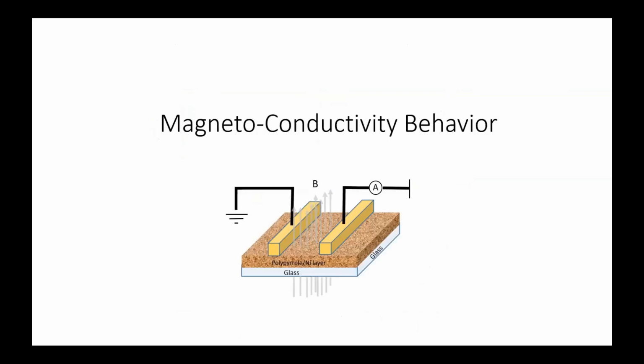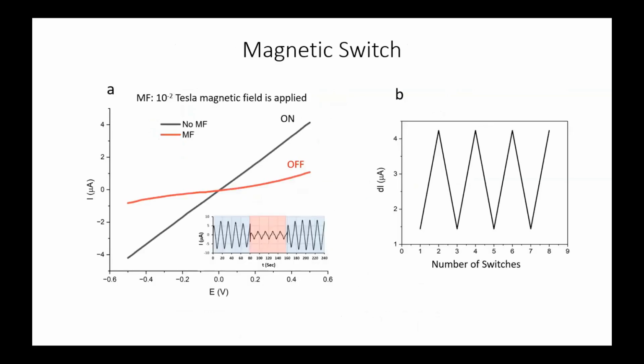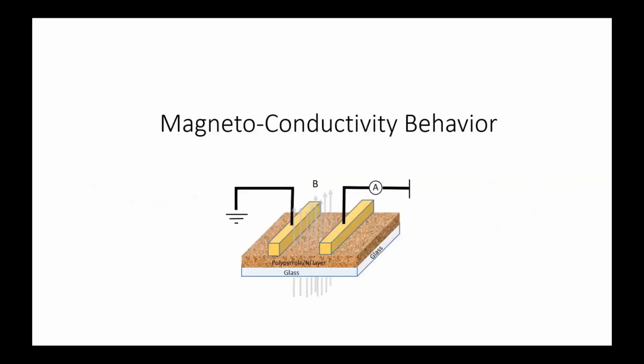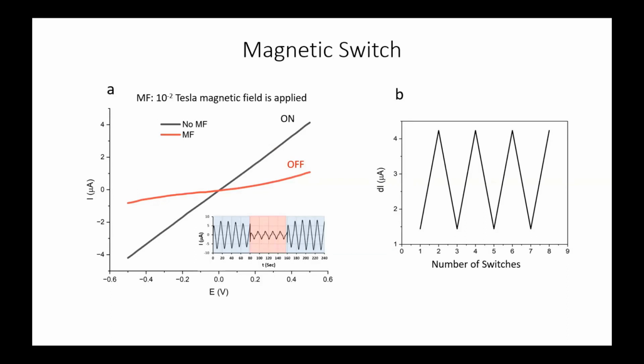Another stimulus is the magnetic field. The magnetoconductive behavior: we found very nice behavior when we apply a permanent magnetic field on the device. We can see a switch in the response of the device, and we can switch from on to off by applying the magnetic field. The magnetic field we apply here is around 100 Gauss, which is 10 to the minus 2 Tesla, and we can see the number of switches that we can apply.